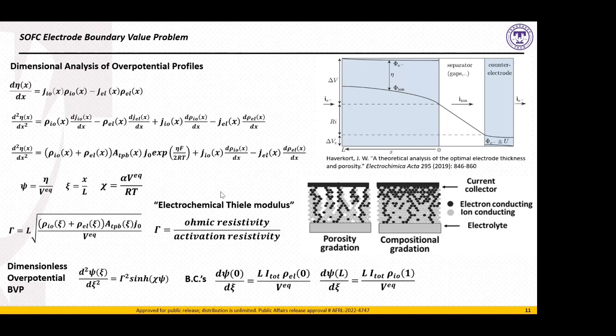But they do a better job at being conductors, we might say. So throughout our numerical optimization, we saw this trend over and over again, that the best performing cells were not necessarily very effective. The overpotential was not well distributed across the electrode thickness. It was mostly concentrated at the surface, at the interface between the electrode and the electrolyte.